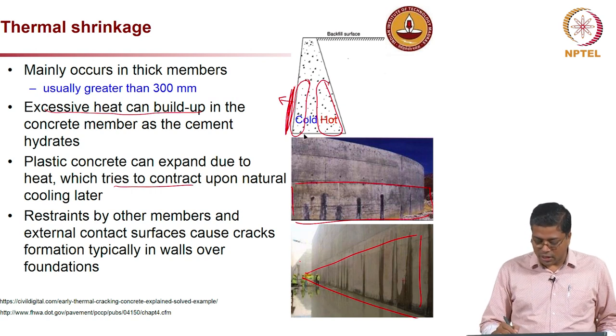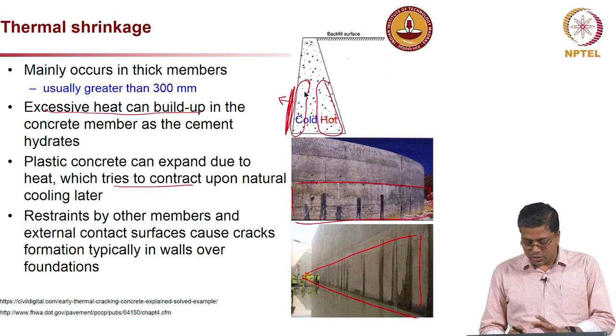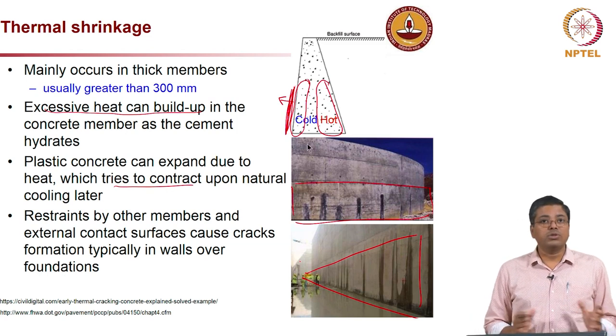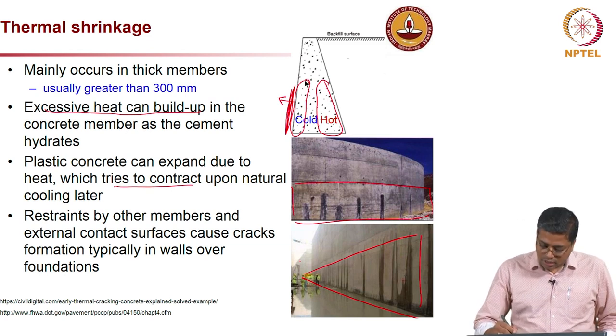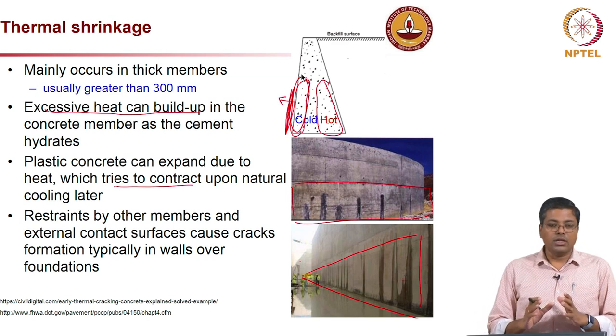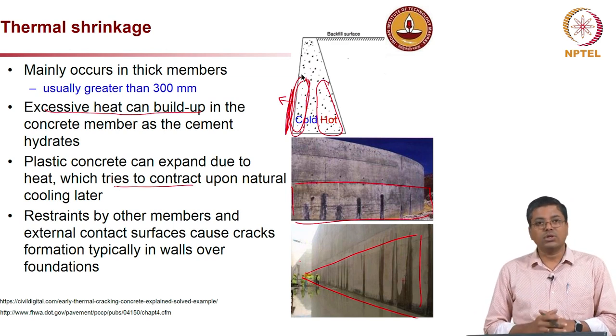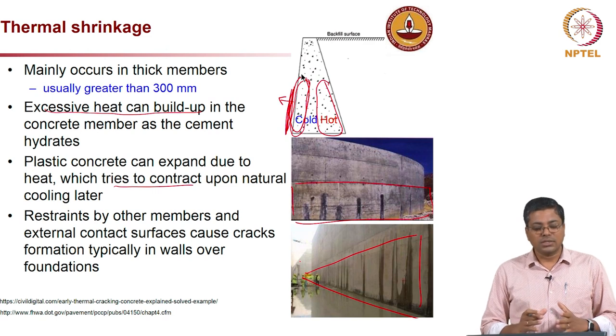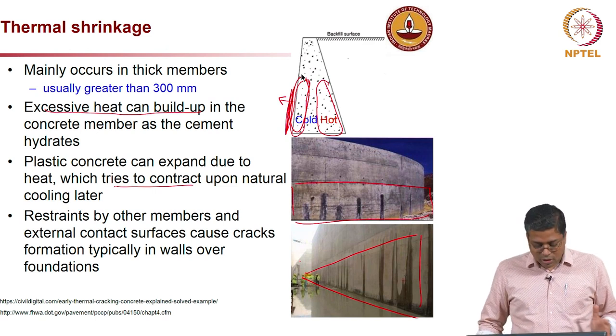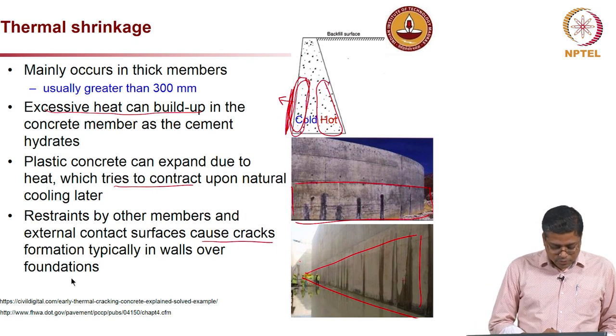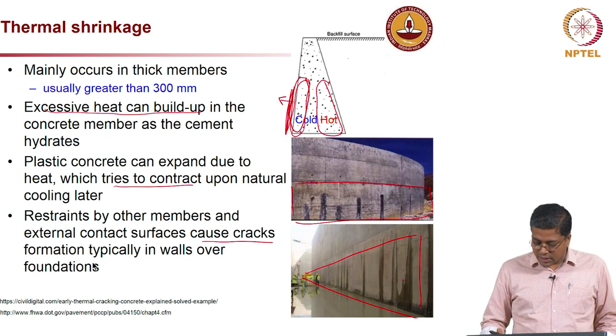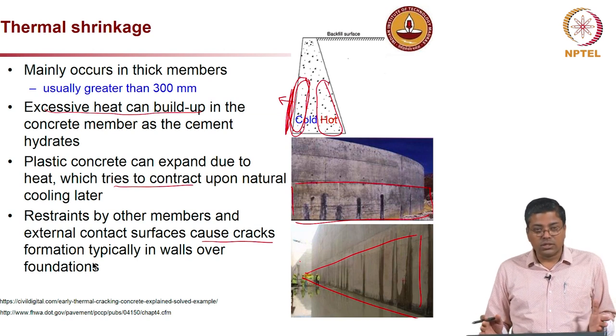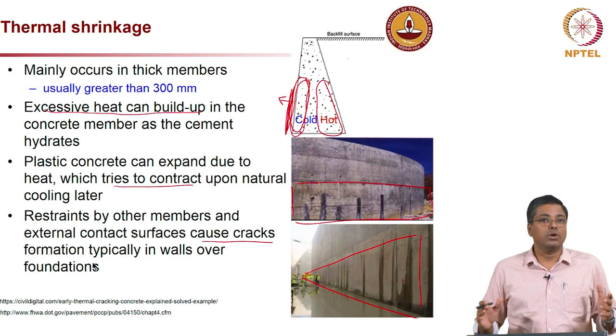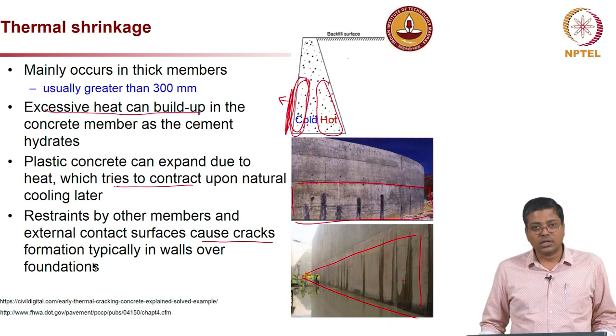If you look at the concrete which I showed in the picture, marked as cold concrete, you can see the other concrete can also provide restraint to this portion. So effectively the bottom portion of this structure is restrained by the other concrete and the foundation, which leads to cracking. And that's the main mechanism. If there is no restraint, then you will not see cracking, but only shrinking. But for most structures, that is not the case.